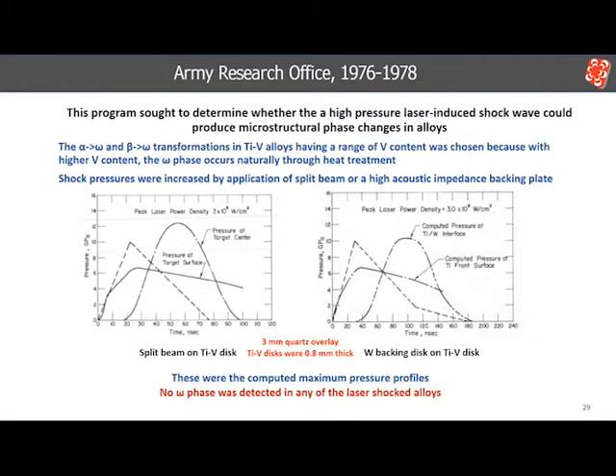Shown on the right is the computed pressure profile of a high acoustic impedance material, tungsten, placed at the back surface of the titanium-vanadium sample. These computed profiles predicted that pressures over 10 gigapascals could be achieved. However, although numerous variations were investigated experimentally, no evidence of the omega phase produced by laser shocking was found. One reason may have been that the pulses were too short to complete the transformation.